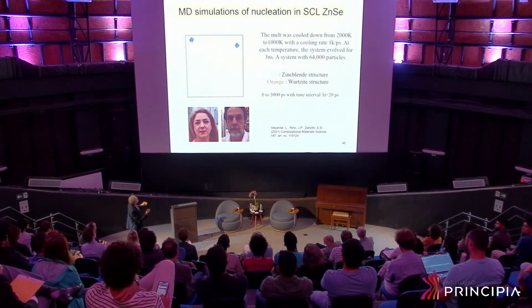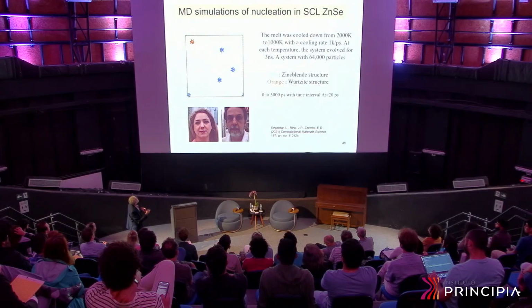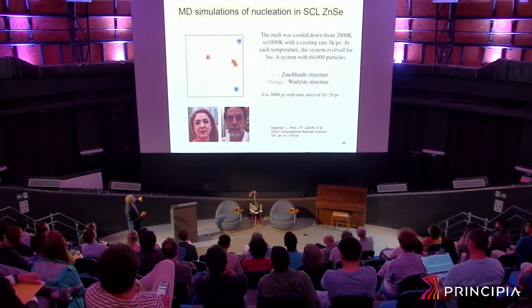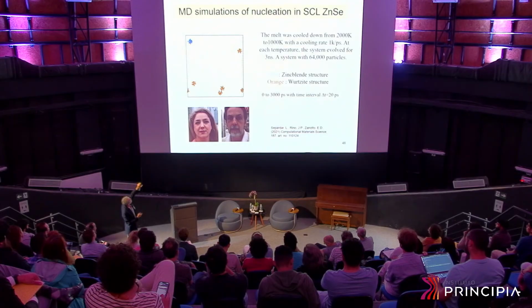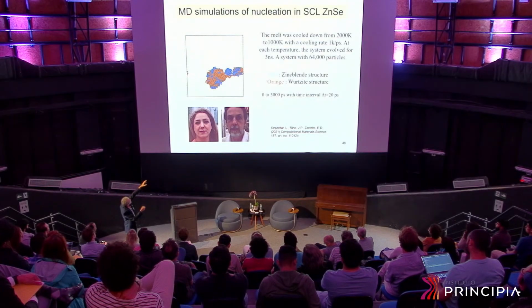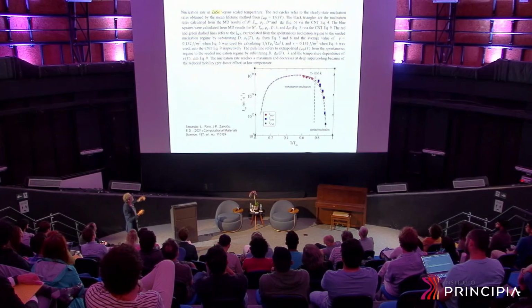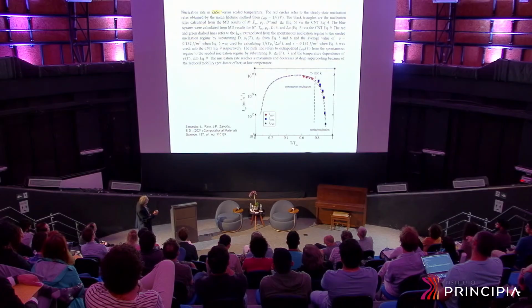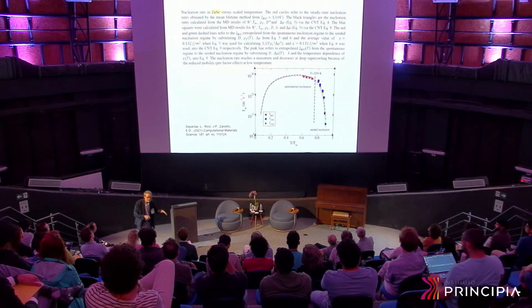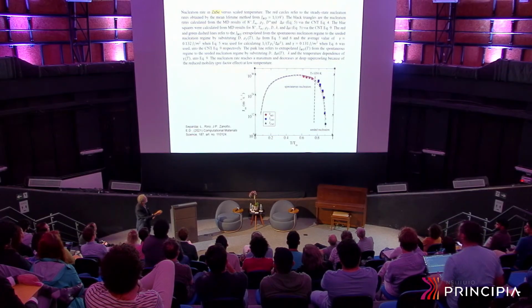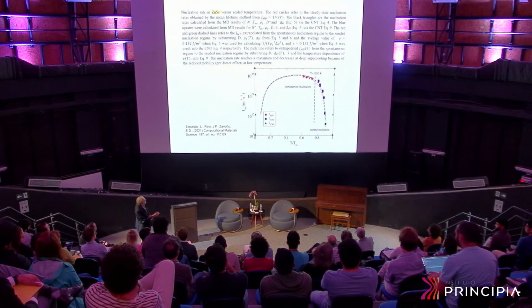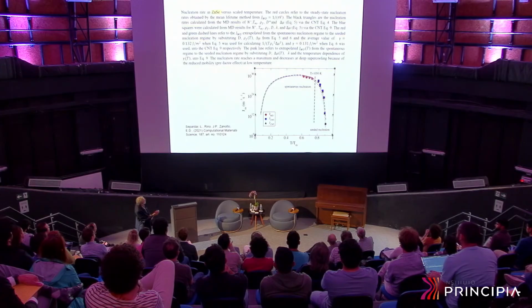This is zinc selenide. You see again the idea of forming, dissolving, forming, dissolving, forming, dissolving. A critical nucleus then forms, and the material grows, and this is the final result. Long story short, the nucleation rate is computed by MD simulation.